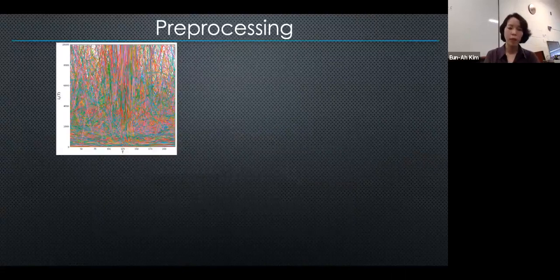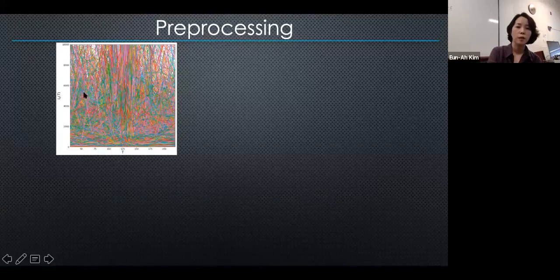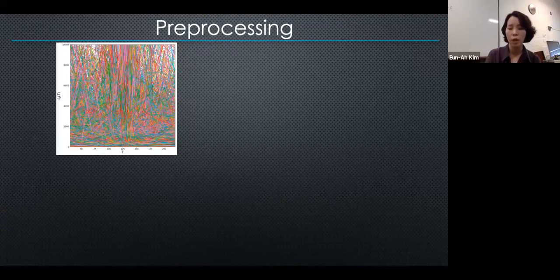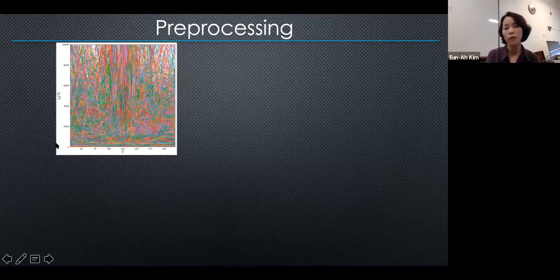Now, the actual X-ray data has various challenging aspects that are more challenging compared to the voice train. One of them is that if you look at this data, this is the raw data plotted, the intensity plotted, and if you look at the scale, it goes over a 10 to the 5 magnitude range. There are signals that are 10,000 times larger than other signals. And this kind of distribution makes it extremely difficult to cluster as raw data. Moreover, there is a lot of noise all over the data. There is a lot of low intensity noise.